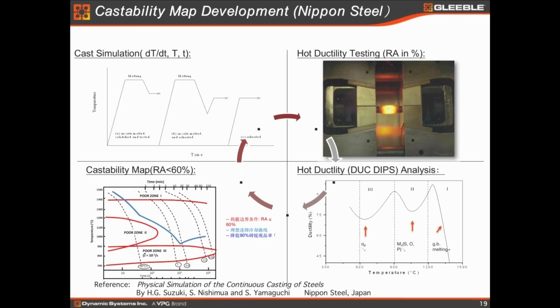And the third low ductility region is associated with the phase transformation from austenite to ferrite. For this steel, they found that ferrite was precipitated at the austenite grain boundaries, and at the temperature when the ferrite forms, the ferrite is softer than austenite. So when you deform it, no matter how small, strain will be concentrated at the grain boundaries, and you might get cracks, and that's how the low ductility arises. So to get rid of this low ductility, they make the steel cleaner and try to avoid the low ductility.